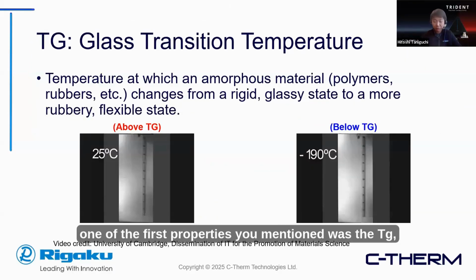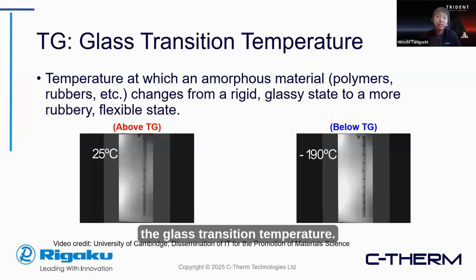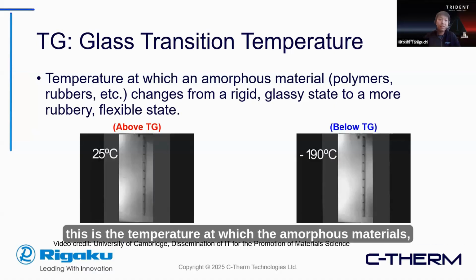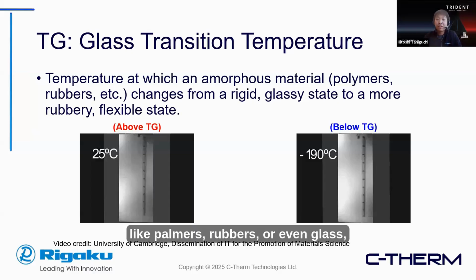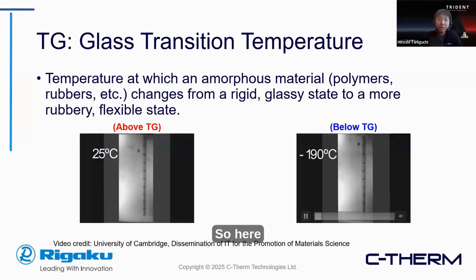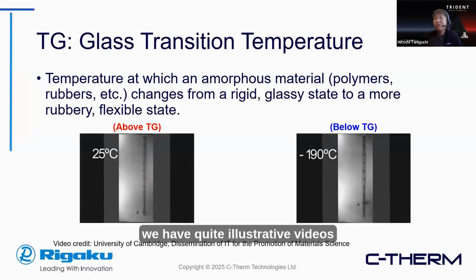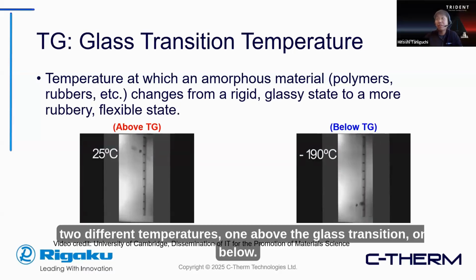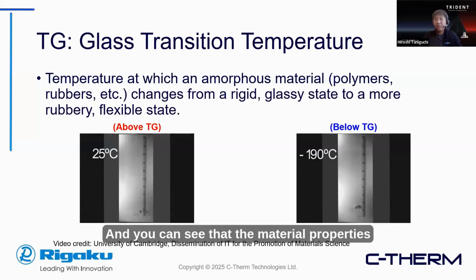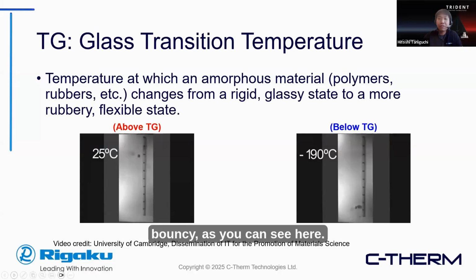So first off, one of the first properties you mentioned was the Tg, the glass transition temperature. Very broadly speaking, this is the temperature at which amorphous materials like polymers, rubbers, or even glass change from a rigid glassy state, hence the name glass transition, to a more rubbery, flexible state. So here we have illustrated videos of a rubber ball being dropped at two different temperatures, one above the glass transition, one below. And you can see that the material properties are drastically different, from a rubbery, bouncing material to being rigid and less bouncy, as you can see here.